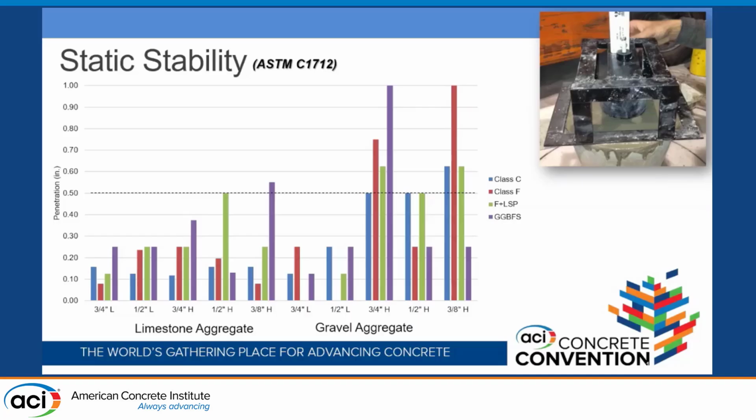Looking at the same performance, which is static stability, but using the penetration test, you can see actually in this, I put the limit here at 1/2 inch. Below 1/2 inch is very stable. From 1/2 to 1 is moderate, and more than 1 is low stability.